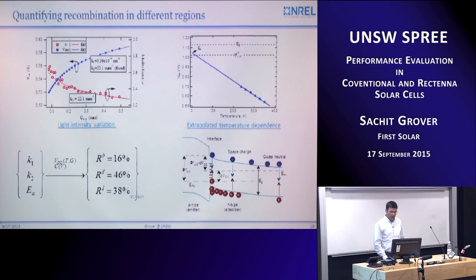More recently, this is just a summary slide with those two techniques. Take the light intensity variation and take the extrapolated temperature dependence here. From those, that gives us three quantities, K1, K2, and EA. And basically, inverting the matrix, I can find out what is the distribution of recombination within the cell at one sun. So for this example of the heterojunction silicon device, the dominant recombination was the space charge, followed by the interface, followed by the bulk. So we had a poor material to begin with because we were growing epitaxially. It had dislocations. And so this is an indication that, yes, here's where the limitations are.